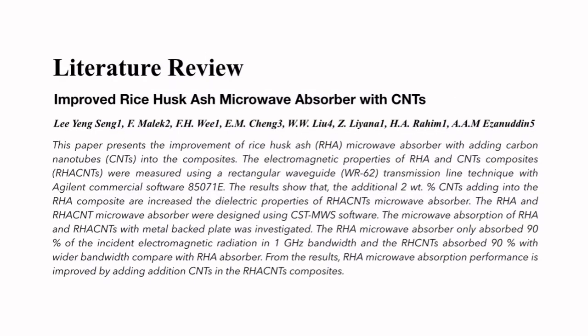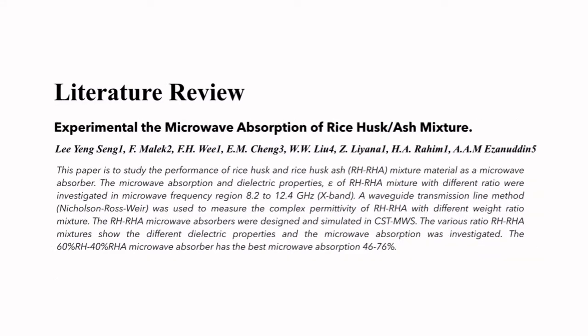For the literature review, this paper, which is titled Improved Rice Husk Ash Microwave Absorber with Carbon Nanotubes, presents the improvement of rice husk ash microwave absorber by adding carbon nanotube into the composites. The results show that adding 2 weight percent of carbon nanotube into the rice husk ash composite increases the dielectric properties of the rice husk ash carbon nanotube microwave absorber.